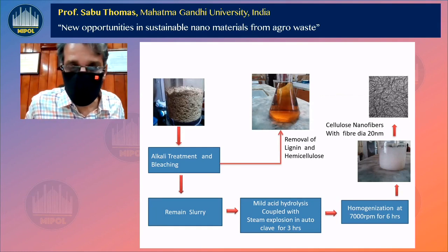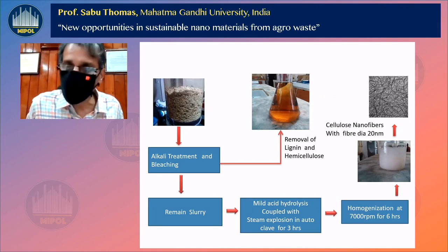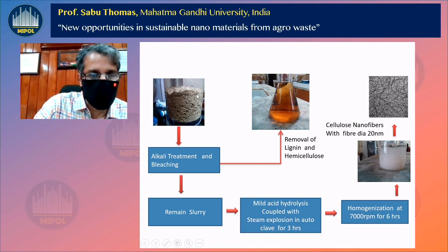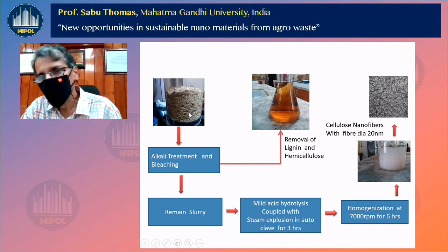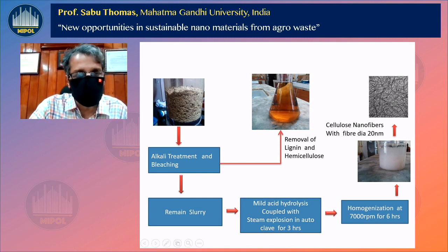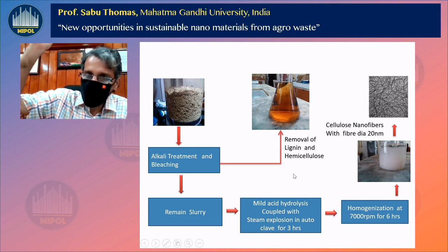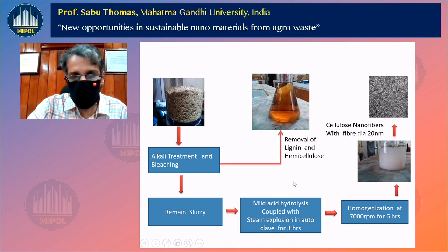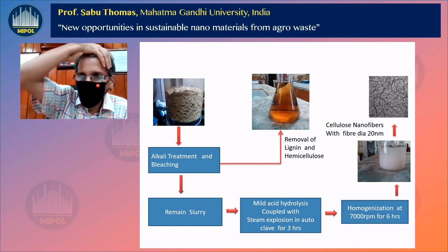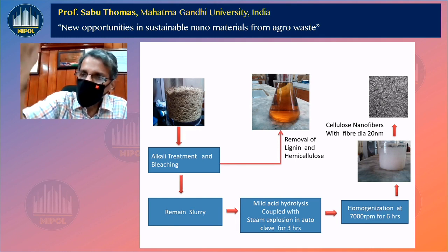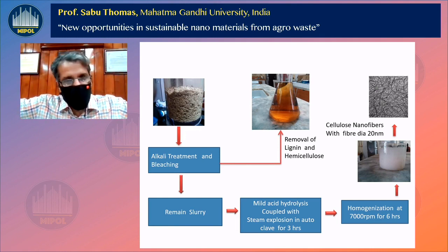So let us see what I do in my laboratory with my group members. My PhD students collect agricultural waste from the plantation. They clean it, wash it, chop it into small fibers, and then do an alkali treatment to remove lignin and hemicellulose. This is again a very important material. You get a slurry, and you go for acid hydrolysis coupled with steam explosion. You can use mild acid or strong acid. If you want nanocrystals, we go for strong acid. If you want long nanofibers, we go for mild acid.